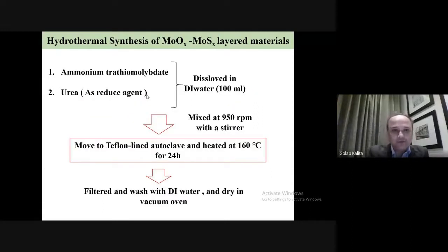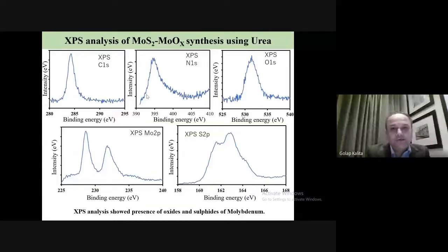Okay, then I discussed some MoS2. I discussed MoS2 synthesis by CVD process. What we can do is some solution process by hydrothermal synthesis. In this hydrothermal synthesis process, we use ammonium heptamolybdate and react with a reducing agent like urea and do the hydrothermal process. If we do this type of process, we get a mixture of MoOx and MoS2. When you have oxide and sulfide, they can make heterostructures between themselves, and it can give very good catalytic properties. We can see from XPS analysis also that we have some MoOx and some sulfide-like structures.